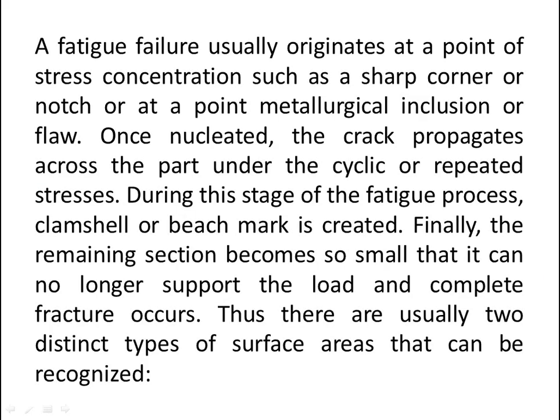A fatigue failure usually originates at a point of stress concentration, such as a sharp corner or notch, or at a point of metallurgical inclusion or flaw. Once nucleated, the crack propagates across the part under the cyclic or repeated stresses. During this stage of the fatigue process, clamshell or beach marks are created.